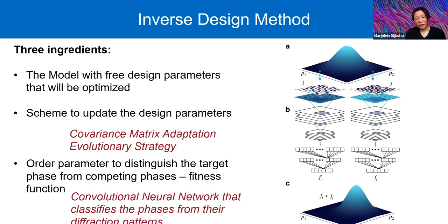So in order to determine whether you are close to the target phase, we use a convolutional neural network that can classify the phases according to the diffraction pattern. I already told you that in order to recognize the quasicrystal, you can look at the diffraction pattern. It has a rotational symmetry that is forbidden for the crystal phase.